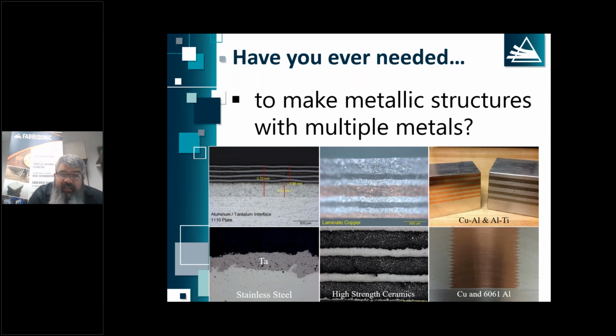On the bottom left, we have tantalum on the stainless. This is actually more of a cladding application. But again, because of the low temperature nature, we can clad a thin layer of highly corrosion resistant tantalum onto a less expensive base of stainless steel. Other applications are gradients. We make armor products that are gradient. We make gradients that go from one CTE to another. The sky's the limit in kind of engineering new materials by layering dissimilar metal layers.